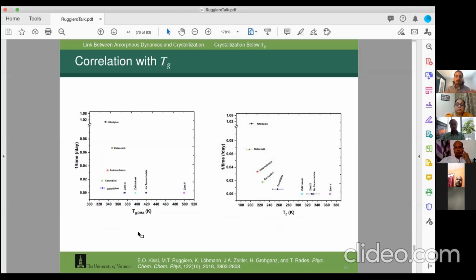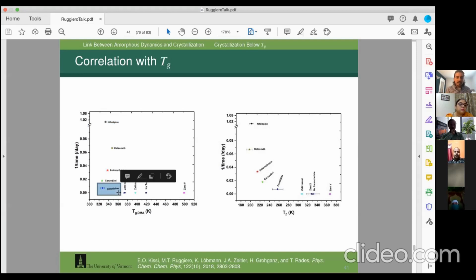If we make these molecules amorphous and leave them out, this molecule here, nifedipine, crystallizes instantly, whereas this molecule here, which has the same primary glass transition temperature, crystallizes much more slowly.